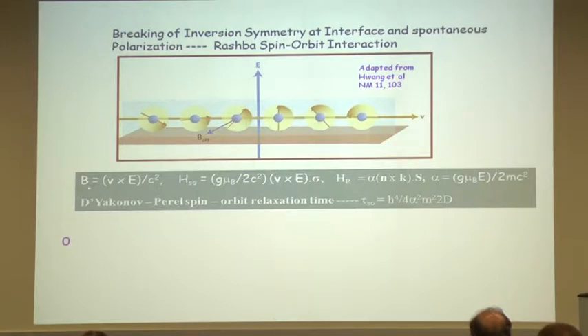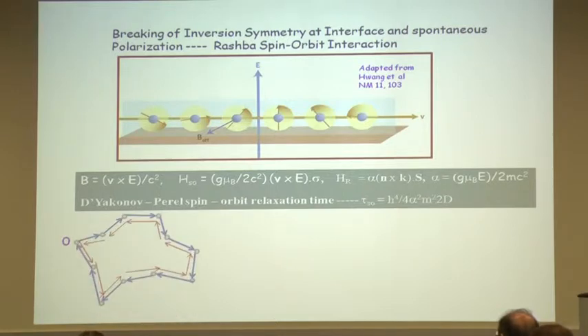And you can write down the B field because of this, it comes from special theory of relativity. And one can write down the Rashba Hamiltonian. And you see that the Rashba spin orbit interaction relaxation time depends on the strength of the interfacial electric field and the diffusion coefficient of the electrons. So it's a very exciting problem, happens purely because of the interface. And one important